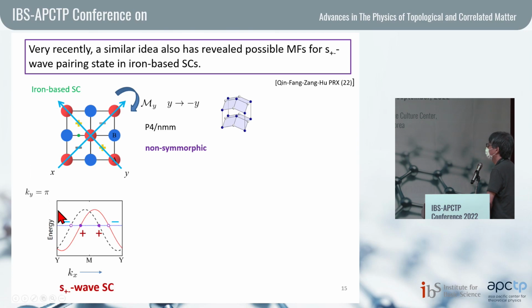And here I show the spectrum along this mirror invariant momentum. As you can see, this is the Fermi level. Around the M point, we have two Fermi surfaces, a smaller one and a larger one. Now we are considering the S plus minus wave superconducting state. The gap function has opposite sign between the smaller and the larger Fermi surfaces.